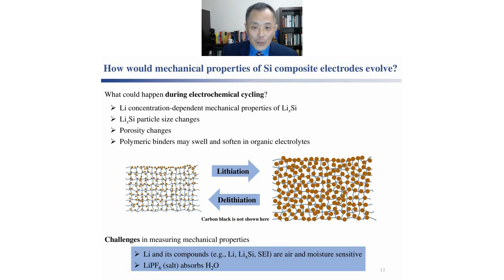This motivated us to study the mechanical behavior of composite electrodes. There are a number of contributing factors that may affect the overall mechanical behavior of the composite electrode. For example, as lithium enters the silicon, it forms an alloy. One can expect the mechanical property of this alloy to change as a function of composition. And as I mentioned, there is substantial volume change of the particles, which can also cause porosity change in this composite electrode. Furthermore, the polymeric binders can soften under the influence of the organic electrolyte. So which of these factors are more important is something that we wanted to figure out.